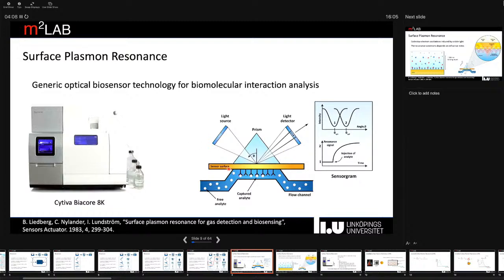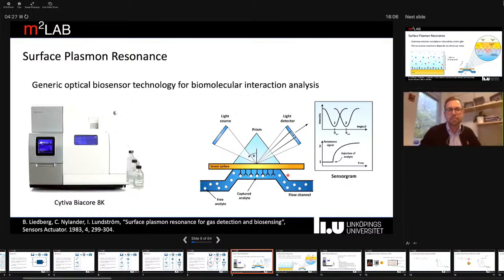which is essentially an optical technique that uses the properties of propagating surface plasmons at the metal dielectric interface, such as this gold surface that we see here. And then we can turn this into a biosensor by immobilizing biomolecules on the metal interfacing the medium around the metal, and then detect ligand-analyte interaction as it occurs on the surface. Essentially what we monitor are changes in reflectivity as we change the refractive index in the vicinity of this surface, so a shift in the reflectivity of light irradiated at the surface. And we can do this detection in real time, so look at analyte-ligand interaction as it happens on the surface.